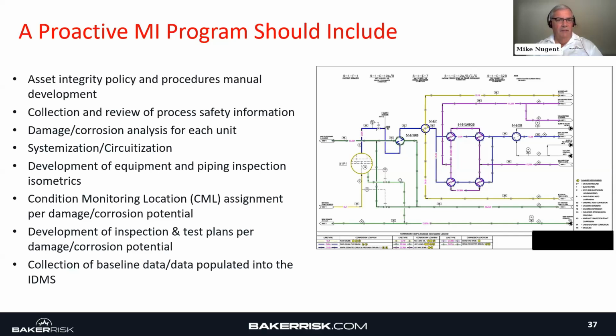But the condition monitoring locations try to capture the areas where you have damage mechanism locations that can be measured by thickness, and you develop inspection and test plans for the damage mechanism corrosion potential based upon the severity of that damage. Usually that's not time-based. Dan talked earlier about risk-based inspection versus time-based inspection.